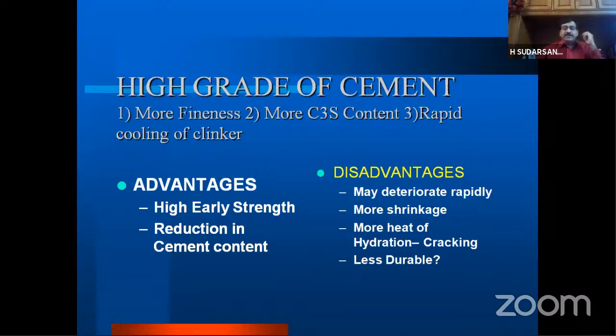What is high grade cement? If you take a 53 grade cement, it has more fineness and more C3S content. This is achieved with rapid cooling of the clinker in the cement manufacturing stage. So if you choose a high grade cement, we get high early strength, but you have to focus on how to reduce the cement content using a high grade cement. That is the mix design. In the mix design, you have to see that you can reduce the cement content by using the high grade cement to achieve economy.